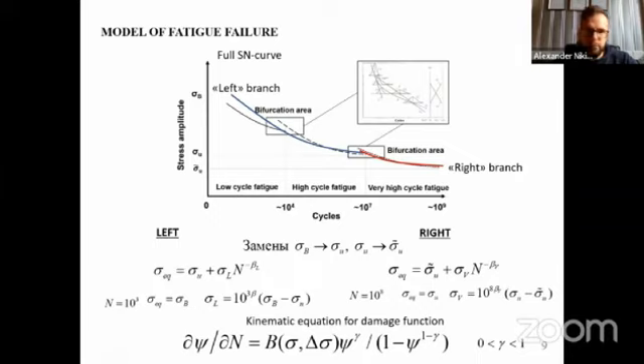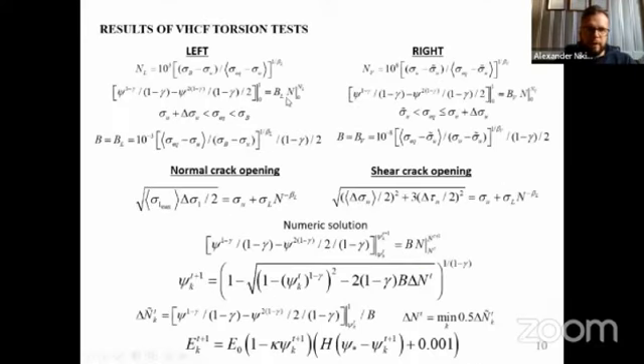We use the idea of the full SN curve with the left and right branch. The right branch relates to very high cycle fatigue. The left branch we relate to the classical mechanism mainly for low cycle fatigue, because we are always working at a relatively high stress amplitude here. In this case, we extend our knowledge about high cycle fatigue to very high cycle fatigue, and we introduce a similarity in the shape of the SN curve. We introduce a kinetic equation for the damage function. It means that we describe the material locally at a point, and we follow the degradation of the material, and then link the degradation, described by the damage function, with the elastic moduli of the material. We associate this degradation of the material with normal crack opening and shear crack opening.